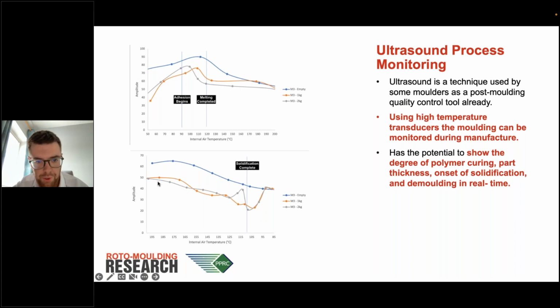And the same thing then during the cooling cycle. You don't really see too much change, which you would expect, until the solidification is complete. And it looks as though something was going on at this point. And then towards the end of the cycle, in and around 100 degrees, there's this return of the amplitude of the signal, which returns back to this blue trace. And you can imagine that as though you are removing the sponge from the bell, or in this case, you're removing the plastic from the surface of the metal, and that sound wave then increases in amplitude, and you get all of your ringing back again.